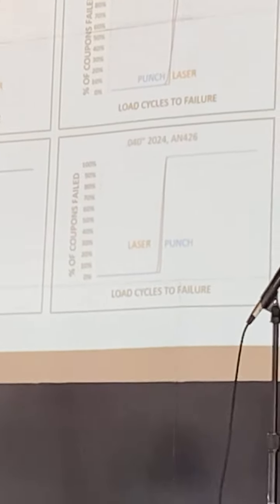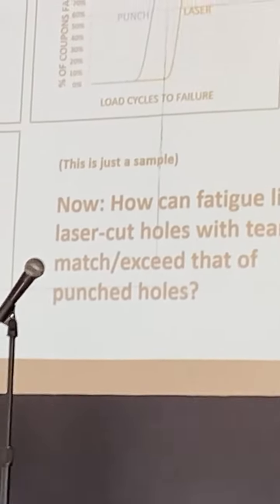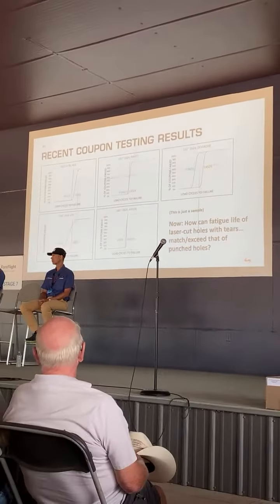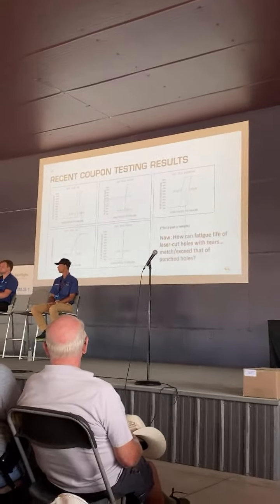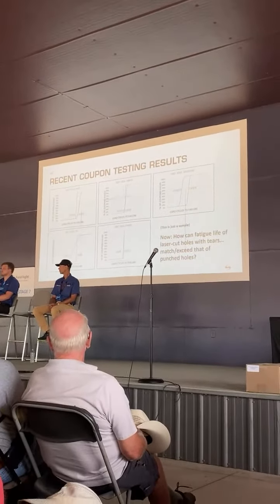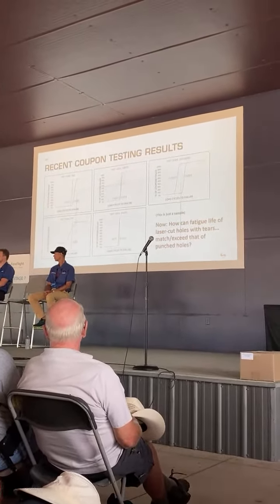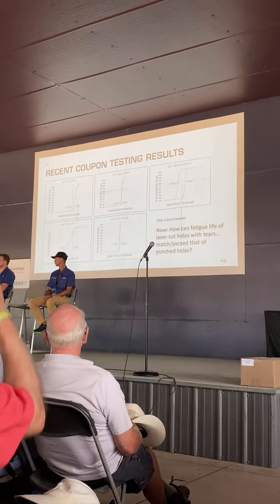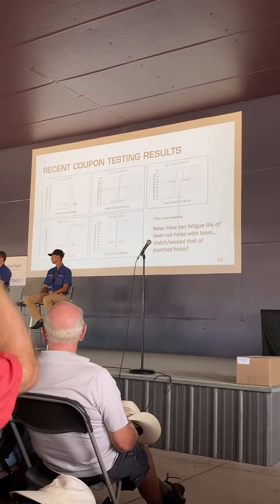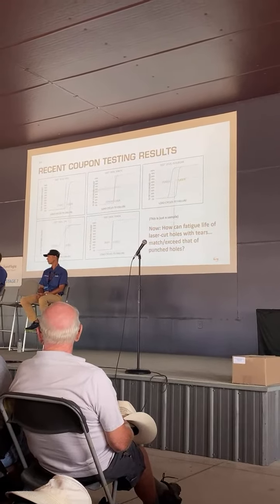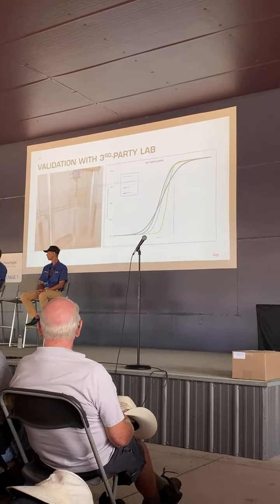We're also testing laser against laser. There was some understructure where that happened, or skin to laser, in which case the skins were never laser cut and the understructure was. So what we can see here is that in some cases the laser is lasting longer than the punch. It has a greater life. And that's what we noticed from the beginning, and it is still the case that we're finding now. And I'll get into the further testing that we're conducting.